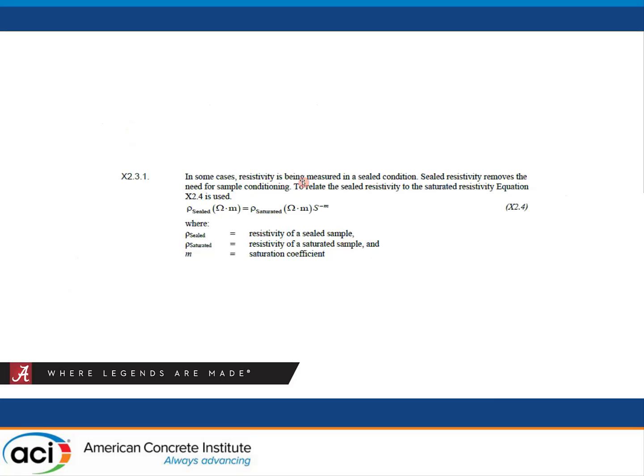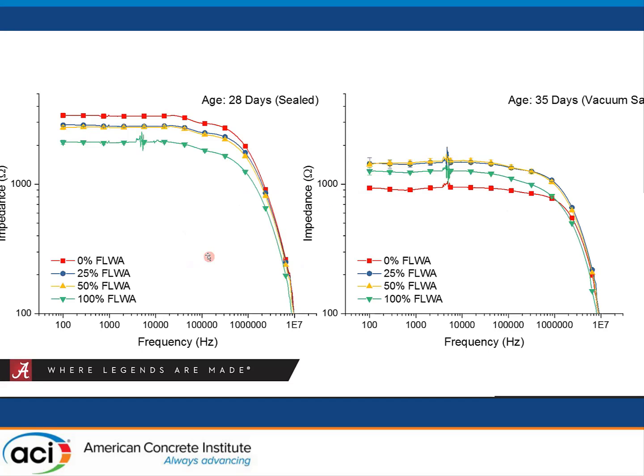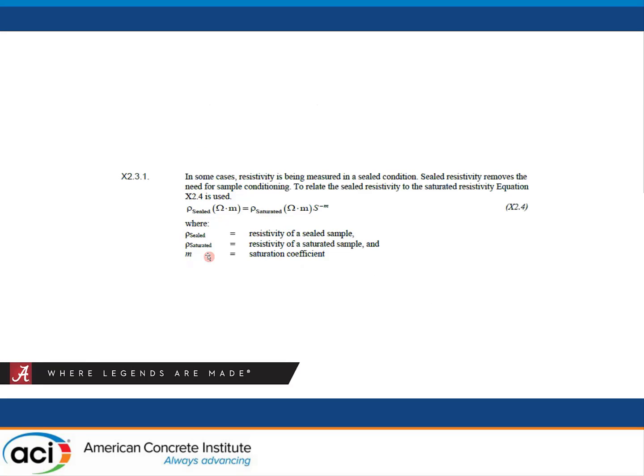And in PP84, it is mentioned that if you have a sealed condition, we can relate the saturated resistivity to the sealed resistivity value using a relationship dealing with the saturation and specifically a saturation coefficient. The documentation goes on to say this coefficient, this m value, has been found to be between 3 and 5 in previous testing. And so, okay, that's great. We could potentially have a way to reconcile this between the sealed and saturated states.